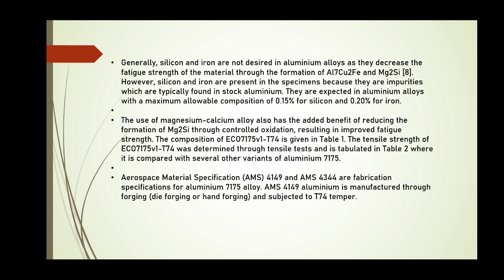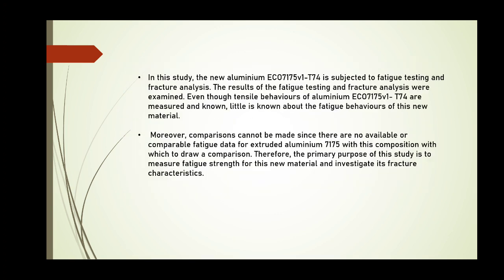So moving forward, generally silicon and iron are not desired in aluminum alloys as they decrease the fatigue strength of the material. However, silicon and iron are present in the specimens because they are impurities which are typically found in stock aluminum. So there is some information regarding the composition of this special aluminum. So we're moving forward to the next.